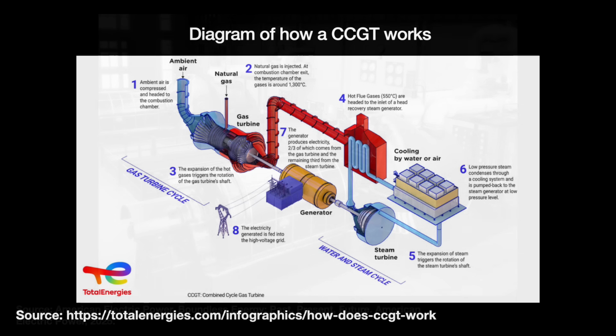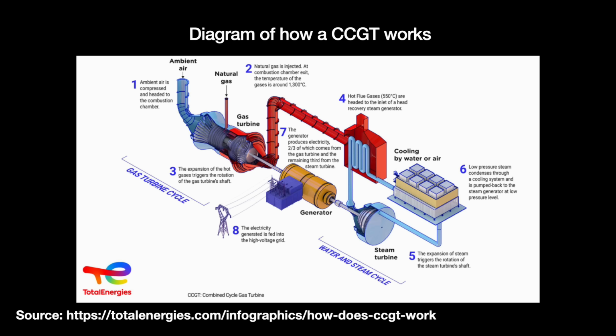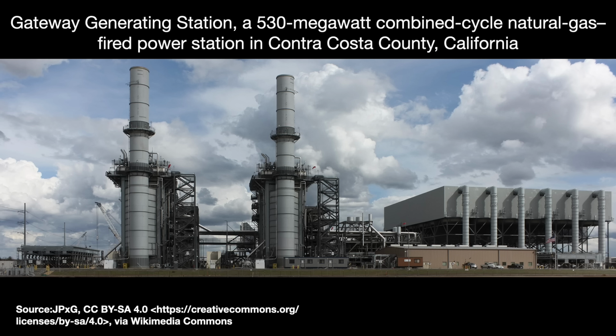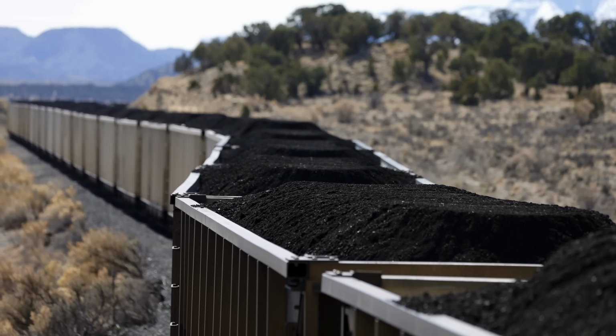There are even versions where the heat in a gas turbine's exhaust is captured to power a steam turbine a la human centipede, a combined cycle gas turbine or CCGT. Measured on point-to-point efficiency, CCGTs beat standalone steam turbines at about 55 to 60% for the former compared to 42 to 45% for the latter. And since they cook with gas directly, you skip a big boiler, though you still need to produce steam. But nothing quite beats coal versatility, storability, and low sticker price. Yeah, CCGTs are more efficient, but dead cheap and plentiful coal beats more expensive LNG, carbon pricing not included.